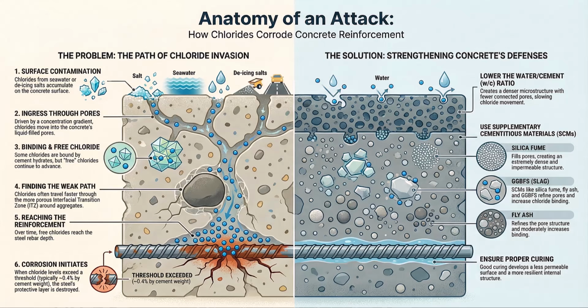So let's look at the data from the sources. Using standard industry parameters, a starting diffusion rate, and a typical activation energy of 35 kilojoules per mole, we can hold the quality of the concrete constant and just change the temperature, which is the one variable we can't control. And let's not get lost in scientific notation. Let's just focus on the comparison, the ratio. Good call. So, if we compare the predicted diffusion coefficient at a cold climate temperature, let's say 10 degrees Celsius, versus the average summer temperature in the GCC, 50 degrees Celsius, the difference in magnitude is just shocking. And what is it? The diffusion coefficient at 50 degrees is nearly 6 times higher than it is at 10 degrees. 6 times. That is the definition of exponential.